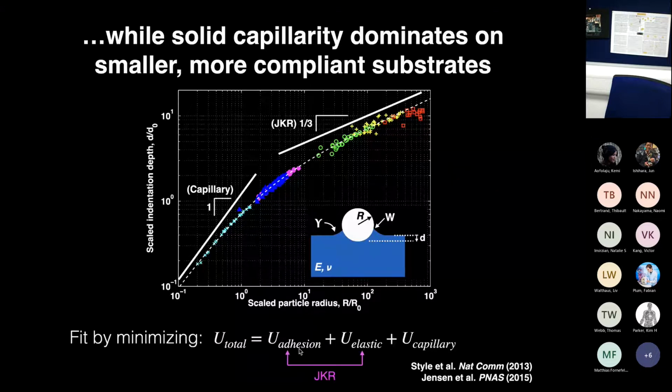And I'll just note that if you only consider the adhesion versus elastic parts, you exactly recover the classic adhesion theory, but by adding in the capillary part, you're able to capture a much broader range of behavior of these very, very soft solids.